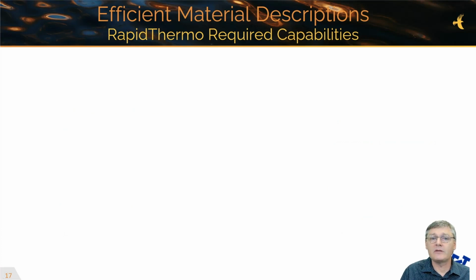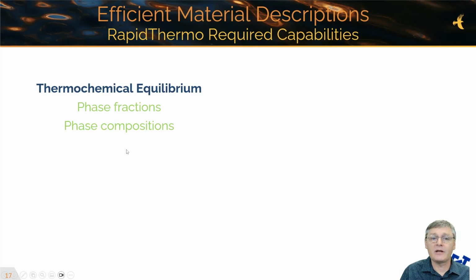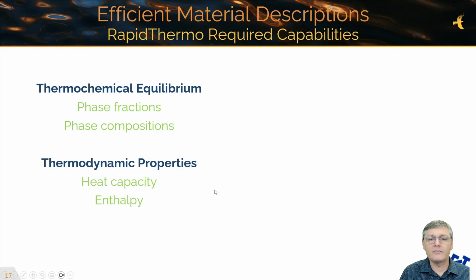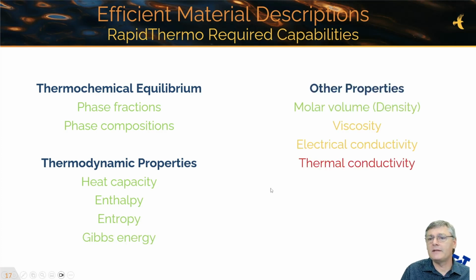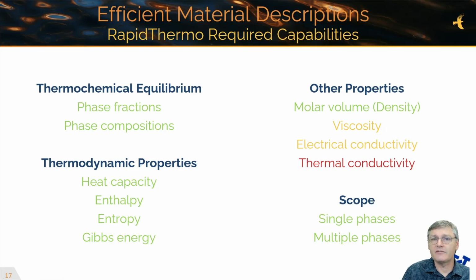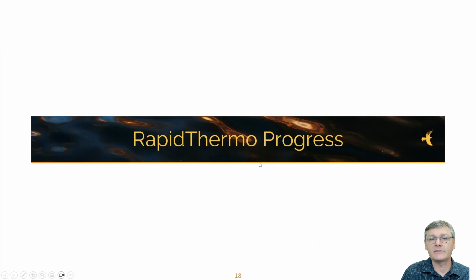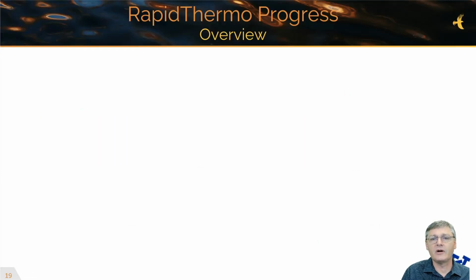So the capabilities that we need from RapidThermo are: thermochemical equilibrium, phase fractions and phase compositions must be calculated. Also properties like heat capacity and enthalpy, which are really important to multiphysics models, but also entropy and Gibbs energy need to be available. And then other properties like molar volume, which will be translated to density, viscosity, electrical conductivity, and then the critical one of thermal conductivity, as I've mentioned. We must also, with the accelerator, describe not just single phases, but also multiple phases, because the multiple phases also influence physical properties.